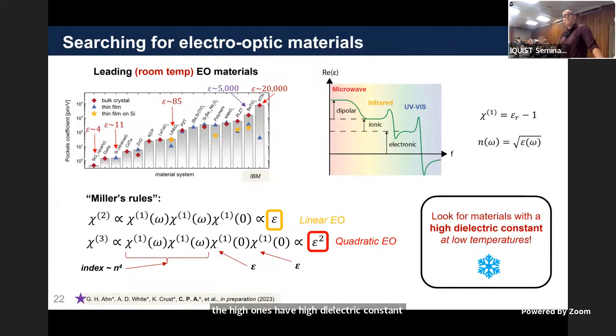And the upshot of all of this is, if you want to do quantum things at low temperature, you can't use this plot, because this plot is only relevant for room temperature. This is the room temperature dielectric constants, the room temperature Pockels coefficient. And so if we want to do this transduction dream, we need materials with a high dielectric constant at low temperatures. Elizabeth.